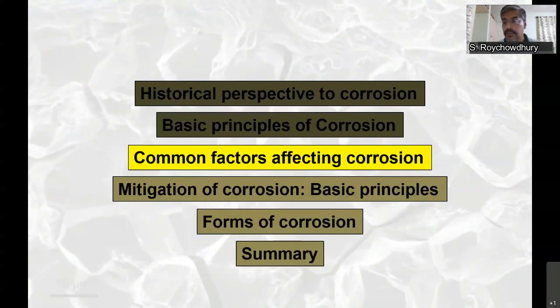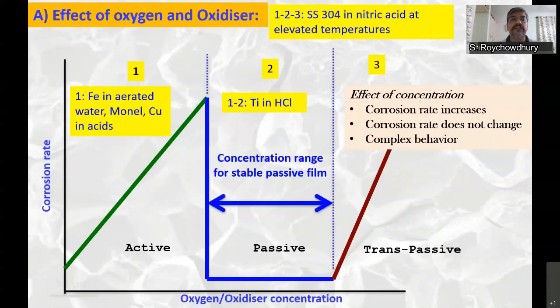Now we come to some common factors affecting corrosion. First we'll see the effect of oxygen and oxidizers. There are various kinds of behavior possible. One is a linear increase in corrosion with increase in the oxidizing agent or oxygen. This is for an alloy which does not passivate, like iron in aerated water.